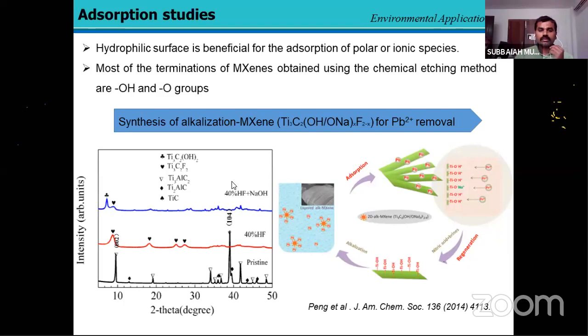Also, further, with the help of hydrogen fluoride. Then this material was used for absorbing lead ion with the initial concentration of 50 ppm. It showed that the absorption was by cation exchange mechanism as well as complexation. Then the material was regenerated using a suitable eluent like nitric acid, and then you will get the original form of MXene. Then we can again incorporate sodium, and then we can utilize it further.